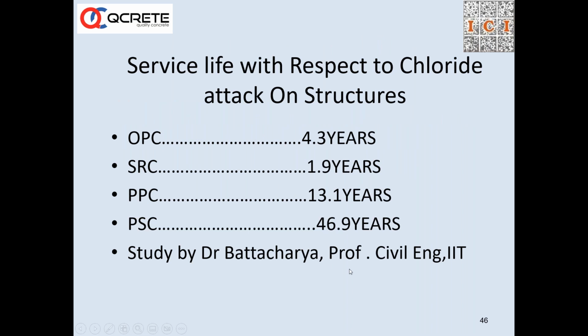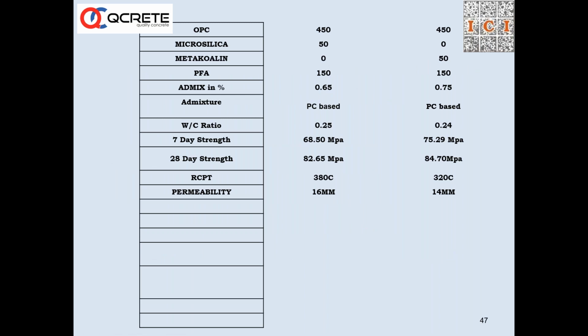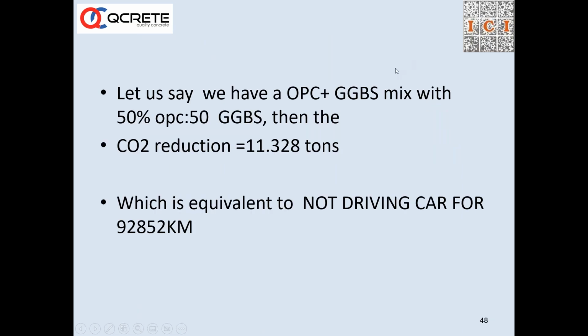Professor Dr. Bhattacharya of IIT has talked about the service life with respect to chloride attack. If a chloride attack happens, what happens to the different materials used? If the concrete is made with only OPC, you can compare that with PSC. So different materials, as we discussed earlier, microsilica, metakaolin, fly ash, can be used to make a highly durable concrete. RCPT values below 500 represent highly durable concrete in a chloride environment like coastal areas. So you can push the concrete to higher durability by using these kinds of materials.